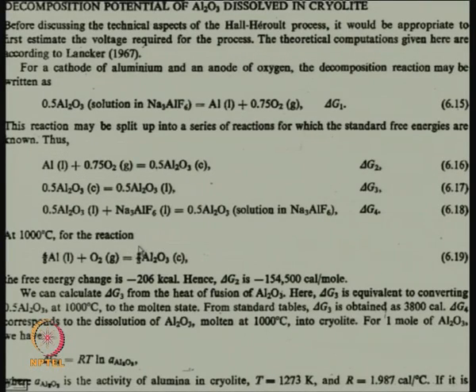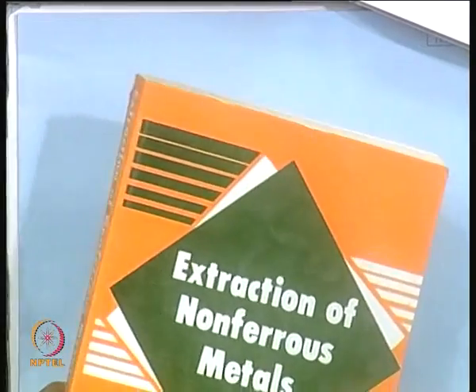Now, let us make some calculations about decomposition potential, and for that I would request you to read up something that I have given in this book on introduction to molten salts, slags and glasses, and also extraction of non-ferrous metals, how you make some simple calculations to find out the theoretical requirement for voltage to dissociate. Now, for that you know a fundamental formula. If you want the free energy of formation, delta G, then it can be equated to minus Z F E, where F is Faraday and E is the decomposition potential. Delta G is equal to minus Z F E. Put the value of Z, which is valency for aluminum, and F, Faraday constant, you get the decomposition potential in volts. So, there is a correlation between free energy of formation in calories and decomposition potential in volts.